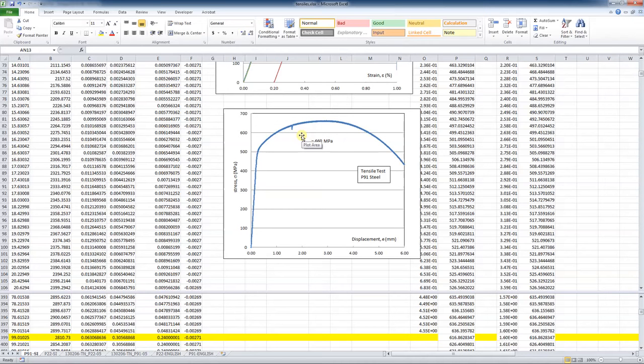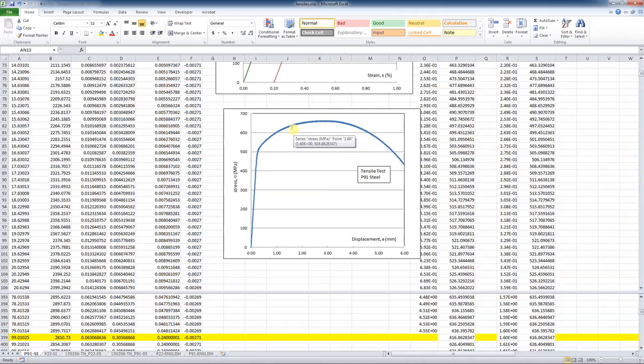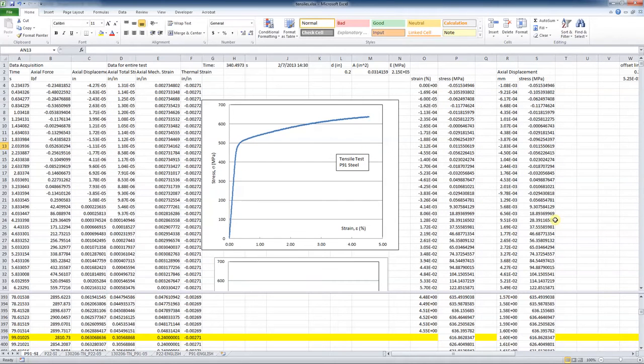That little dip in load around 633 megapascals was when I took the extensometer off the specimen — the extensometer measures strain. When I took it off, the load relaxed slightly because it was in displacement control, giving a little bump downward. The displacement then continued and the load picked right back up and joined the rest of the curve. I don't have strain data beyond the extensometer removal point, so our stress-strain curve is truncated there at about 633–635 megapascals, but we still get close to 4.5–5% strain.